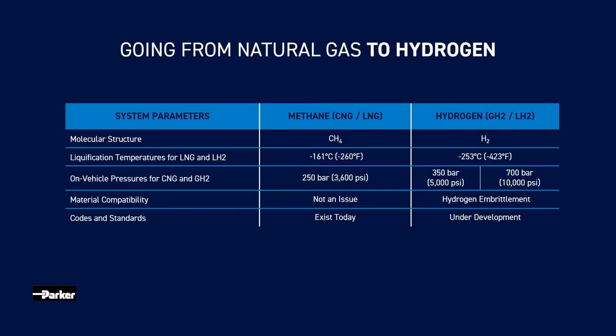The onboard pressures that these gases are stored for methane is typically 250 bar or 3600 psi. And for hydrogen, because you're trying to get that same range, and hydrogen doesn't have the same power density that methane does, that's going to require some higher pressures on board. And currently there are 2 pressures that are being used in the industry, 350 bar and 700 bar.